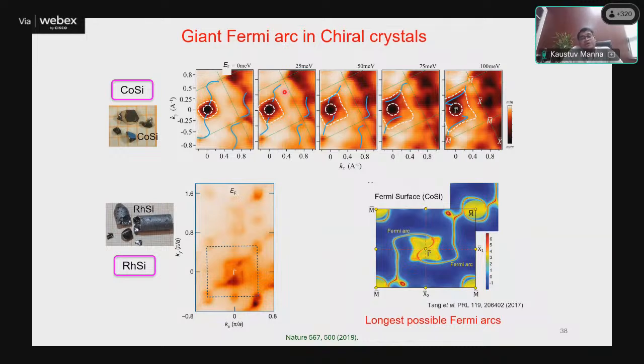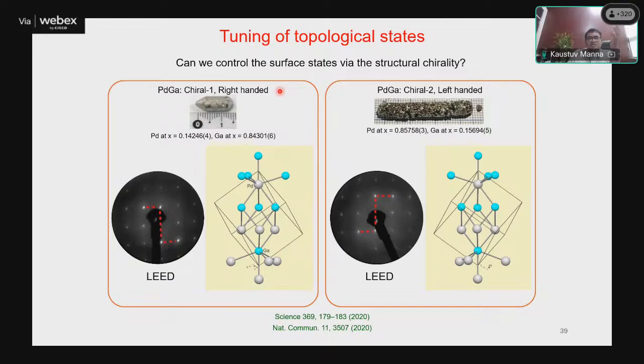Next is, can we control these topological states? How these topological states can be manipulated, which is in the momentum space. So what we do is that I have grown the crystals. One is a left-handed chiral crystal, another one is a right-handed chiral crystal. So the crystal growth part is explained in these papers. From X-ray and also EBSD experiments, not EDX, we confirm the chirality of these. One is left-handed chirality, the other one is right-handed chirality, same composition crystals.